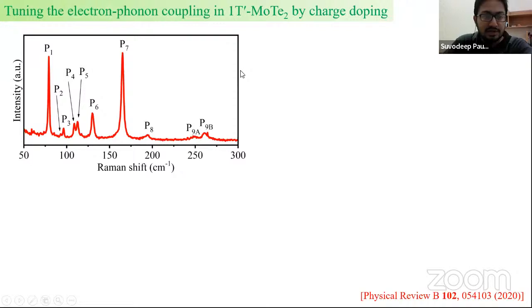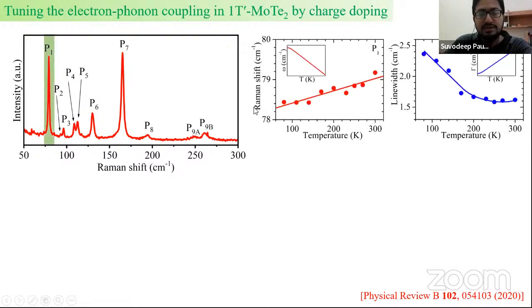So in our study on 1T prime MoTe2, this is the Raman spectrum of 1T prime MoTe2, we saw that this phonon P1 here shows a clear signature of electron-phonon coupling. And that is manifested by an anomalous temperature dependence of the mode frequency and also the line width with respect to the anharmonic behavior shown in the insets. And we could also see the evolution of the electron-phonon coupling strength from the slopes of these anomalous curves.